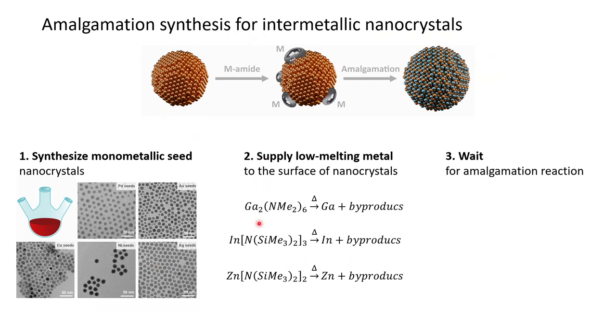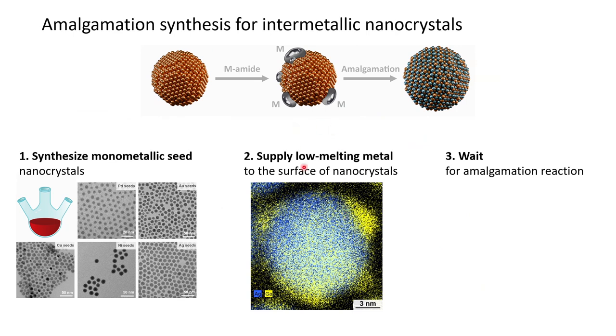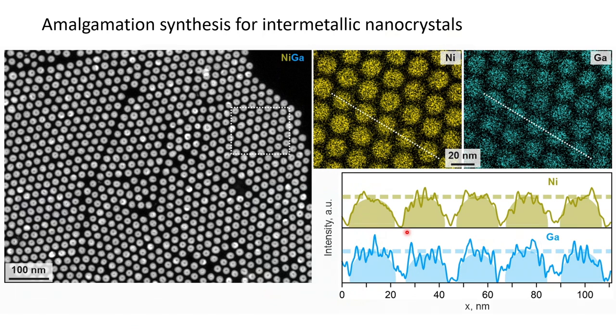We chose alkylamides and silylamides of different metals, because we know that at high temperature these compounds decompose, leaving behind metal and easily leaving byproducts. We were successful with this supply of liquid metal. As you see here on the compositional map, there are yellow regions at the surface of the nanoparticle, which are the gallium islands. As soon as we have gallium there, we trigger the diffusion of the gallium inside the nanoparticle, and the third stage is simple. All we need to do is wait. Fortunately, we don't need to wait very long, because the diffusivity of liquid is much faster than that of the solid. Here you see an example of what we can obtain using amalgamation synthesis. These are nickel-gallium nanoparticles. Again, they have a very uniform size, and from the composition map, you can see that the composition of each nanoparticle is the same. In this case, it's about a 1-to-1 ratio.